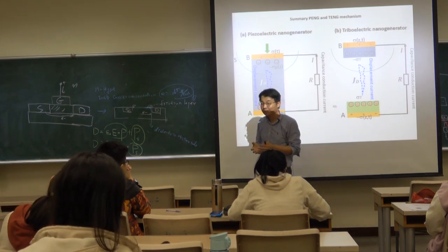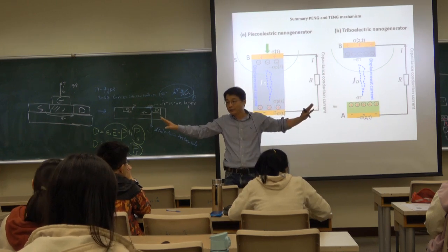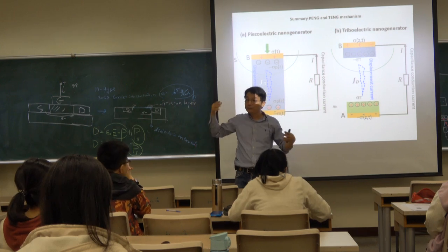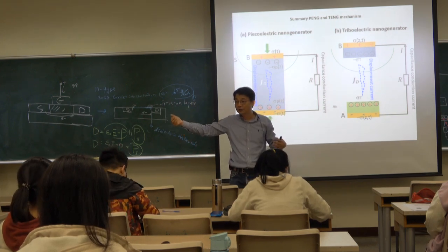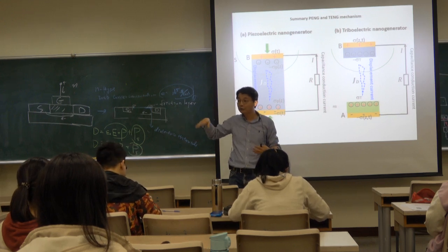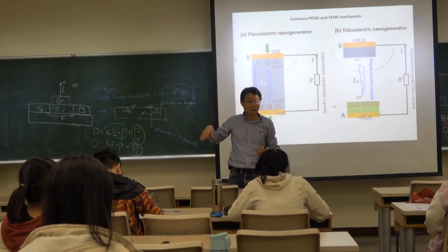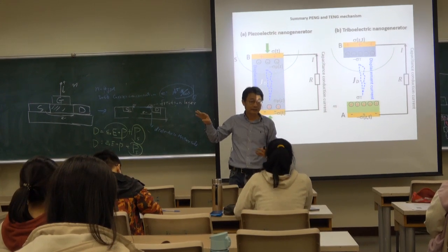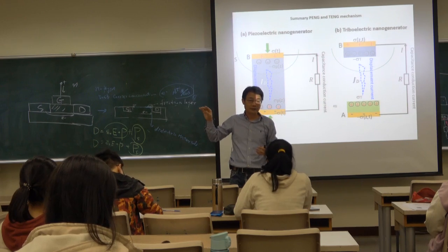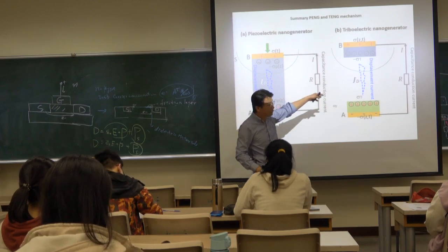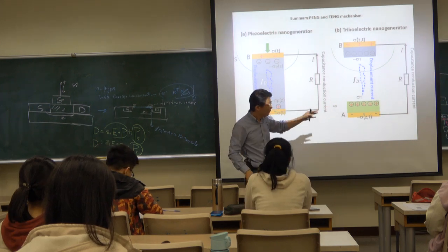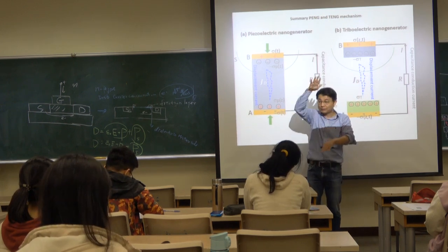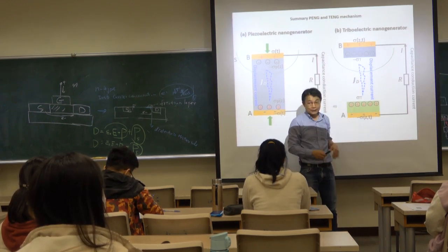So for the summary, I would say both triboelectric materials and piezoelectric materials create the polarization. But the polarization from the piezoelectric material is relative to the non-central symmetry: once we apply the strain, it will create a dipole moment, and this dipole moment can create electricity. For the triboelectric materials, the polarization is relative: the positive charge and negative charge are separated, and create a polarization.